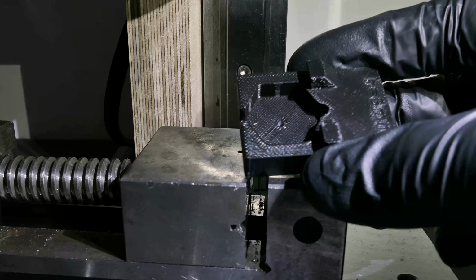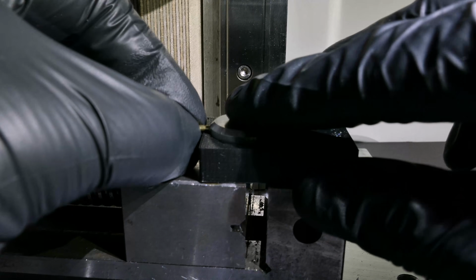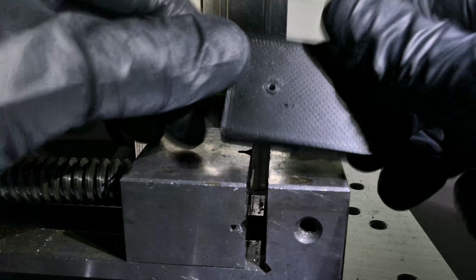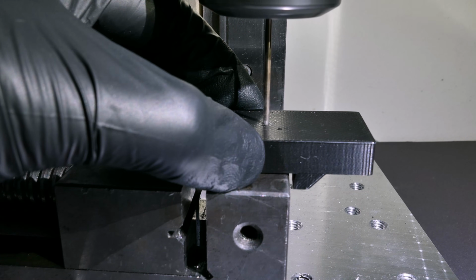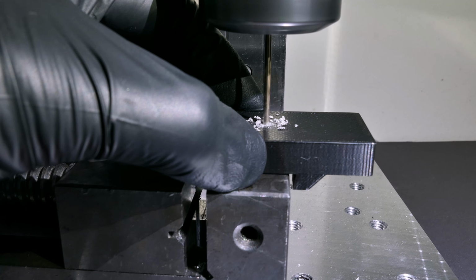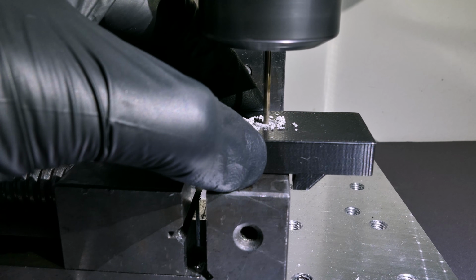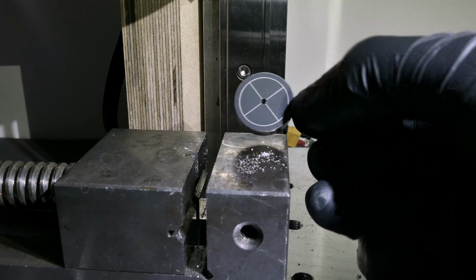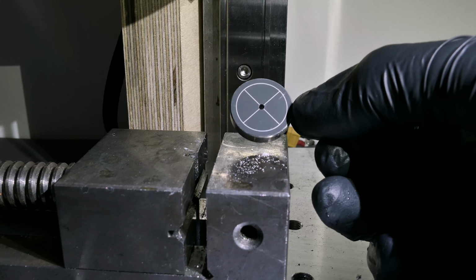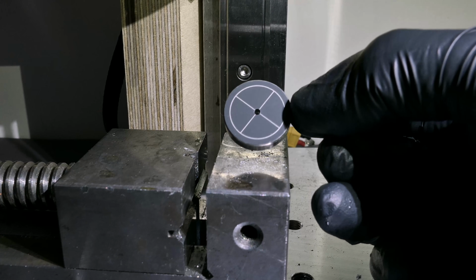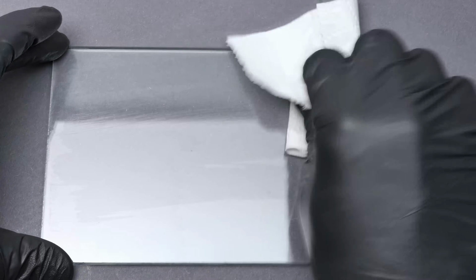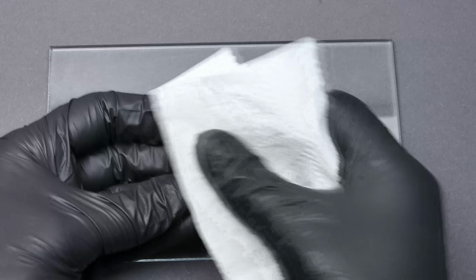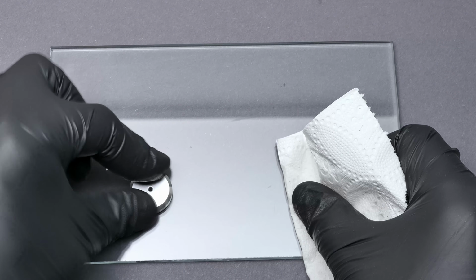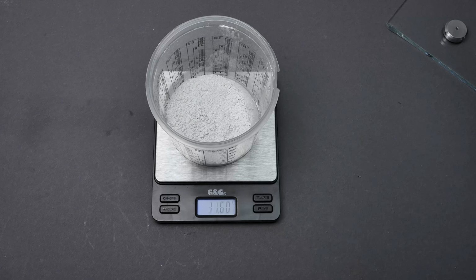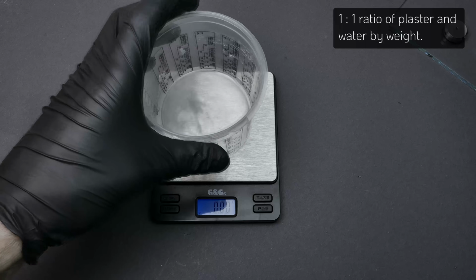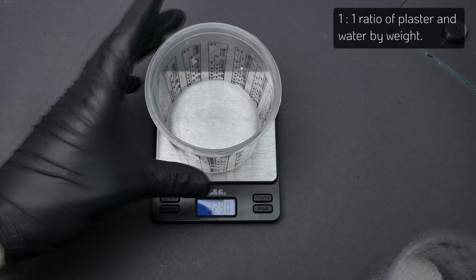The final step in the build process is creating the restrictor nozzle through which air is fed to the underside of the pad. The drill jig is used to drill out the epoxy resin from the center hole. The pad is then placed onto a clean glass surface, and the center hole is filled with plaster to form the restrictor. The plaster should be mixed fairly thin to increase porosity when cured. You can adjust the porosity based on your application and feed air pressure, but I have found a 1-to-1 ratio of plaster to water works well.